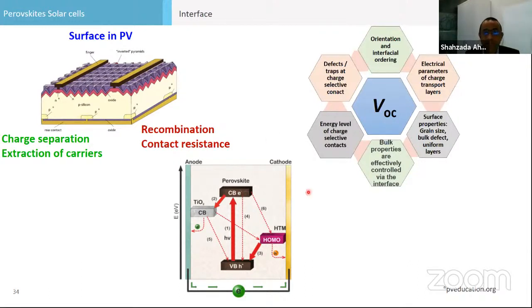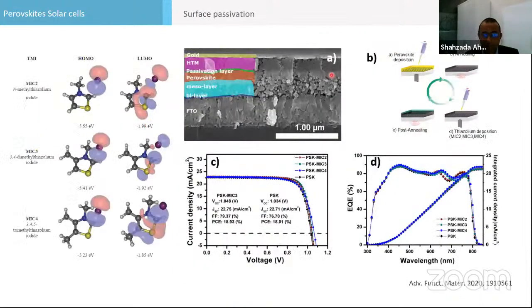We can achieve higher VOC, open circuit voltage. We have to adopt different types of parameters to do that. This is the electrical parameter, the charge transport layer. The increase of the grain size minimizes the defects. The energy level of the charge selective contact, meaning N type and P type, is very, very important. And the defect traps at the charge selective contact, we minimize them. We can increase the VOC.